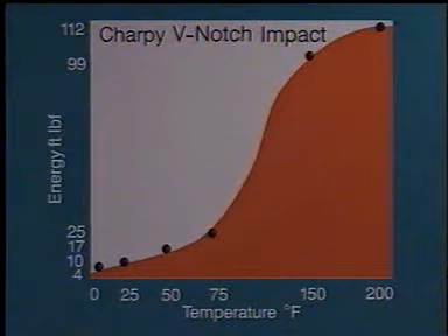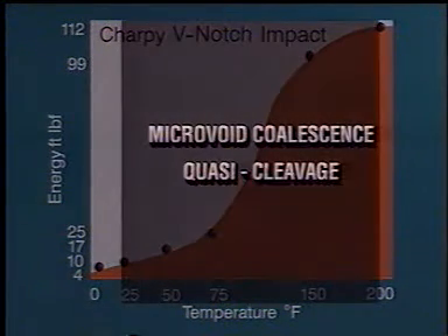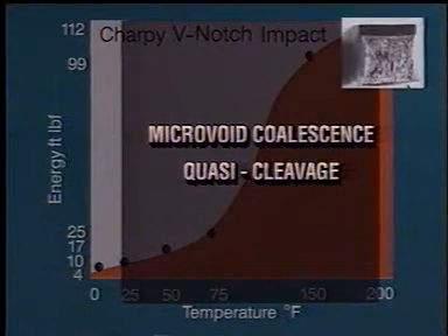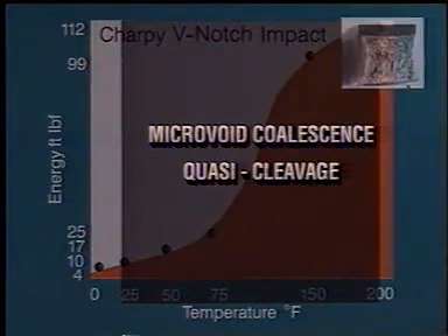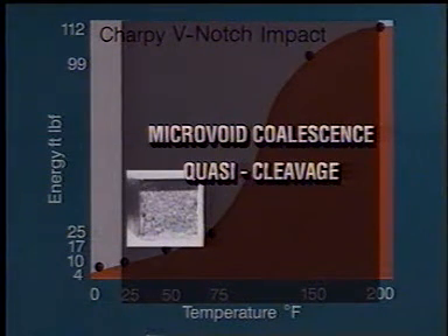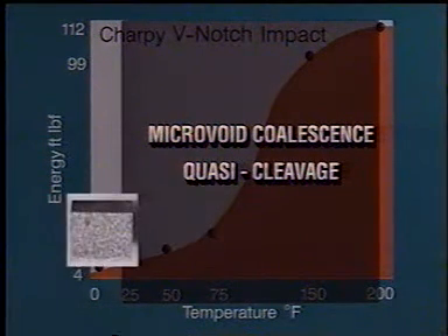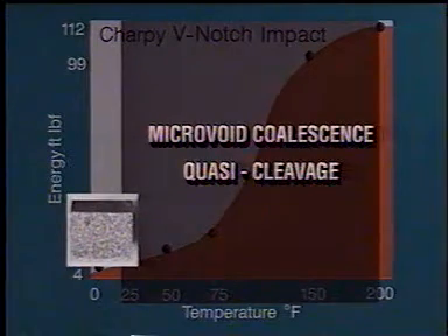At temperatures within the transition range, crack propagation occurs by both microvoid coalescence and quasi-cleavage. This new term refers to fractures that exhibit a rupture between brittle and ductile, with the appearance of mixed dimples and cleavage. The quasi-cleavage is predominantly confined to the central region of the fracture surface.